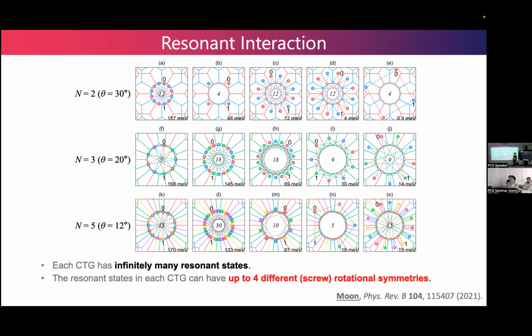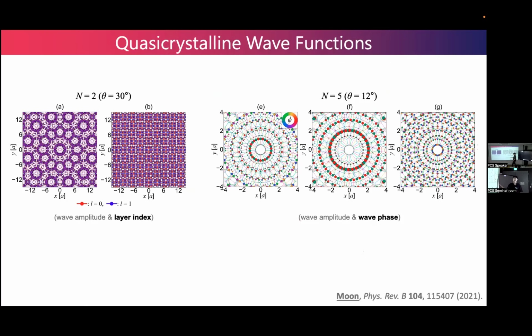But have you ever calculated the energy? Yes. So where is it? I didn't show it because our band structure is plotted using this as the center. This is mapped to the gamma point, but this is away. So I did not show the band dispersion, and this is the wave function. Please note that this is a hexagonal structure, so a 30 degree rotation means 0, 30, and 60 degrees, and 60 degrees is the same as 0 degrees. So the periodic unit is simply the twisted bilayer graphene quasicrystal. Except for the momentum along the z direction, in-plane features are common to twisted bilayer graphene, so this will be observed in twisted bilayer graphene.